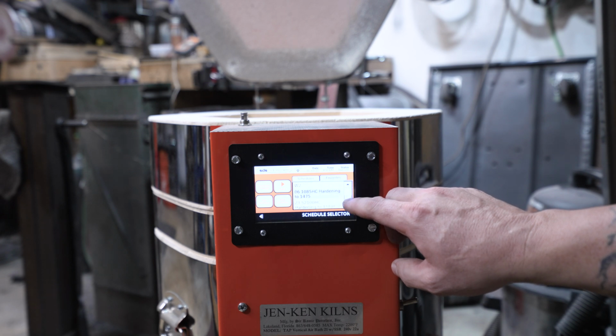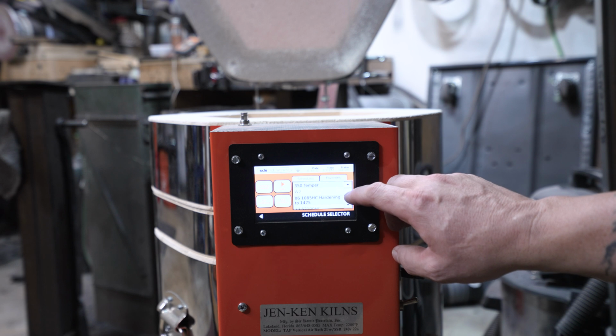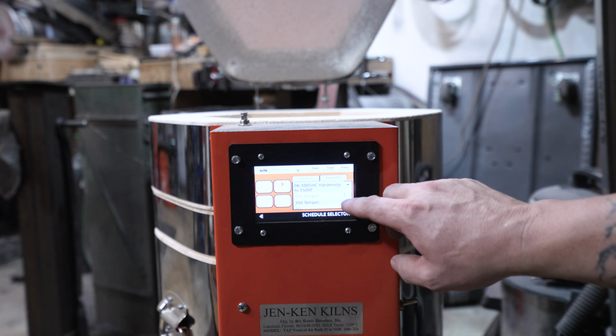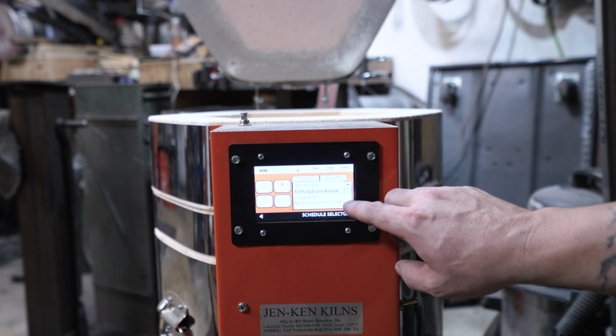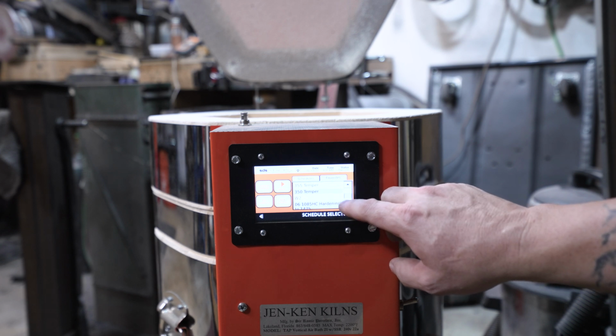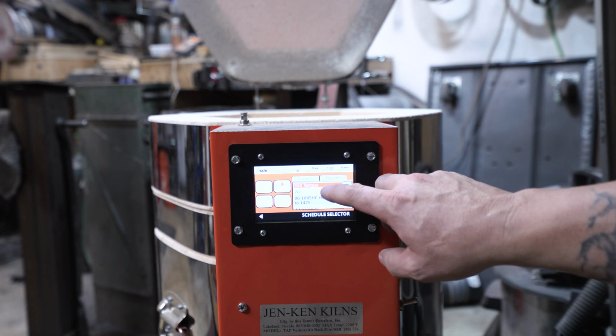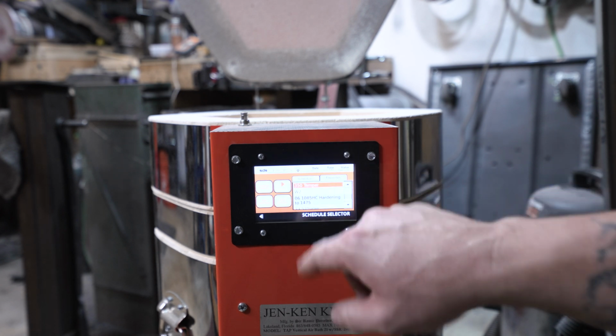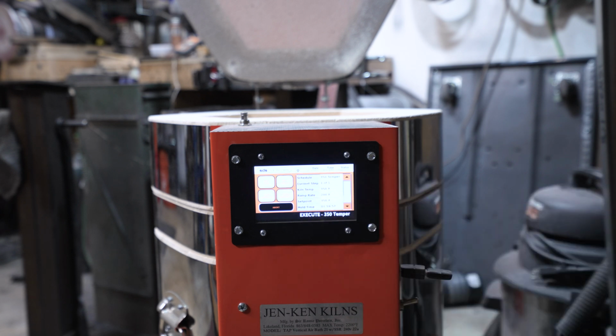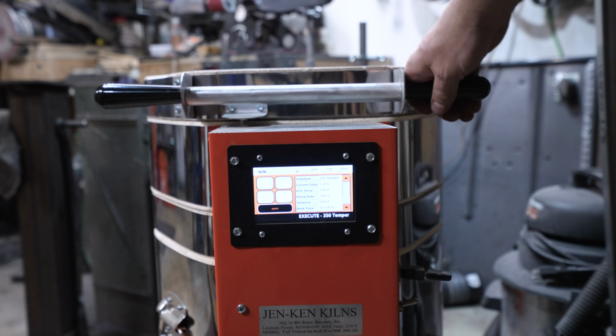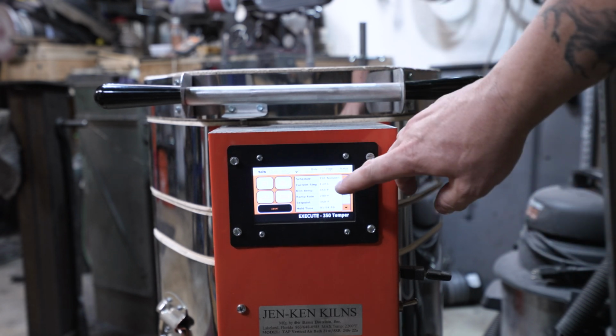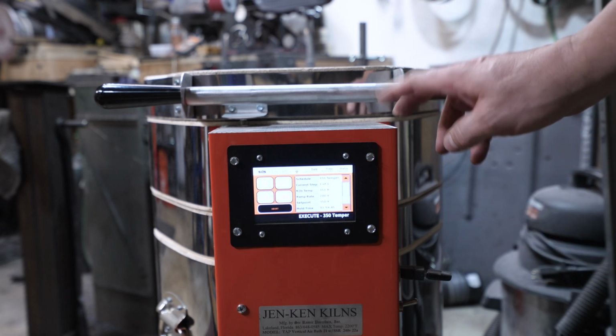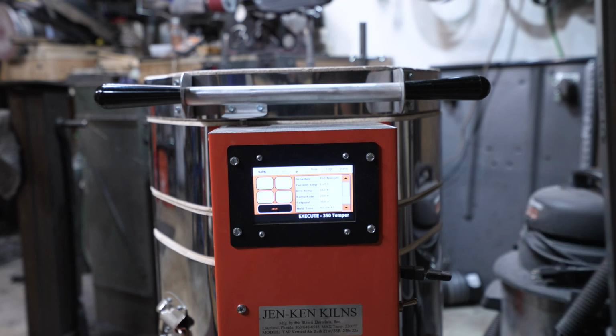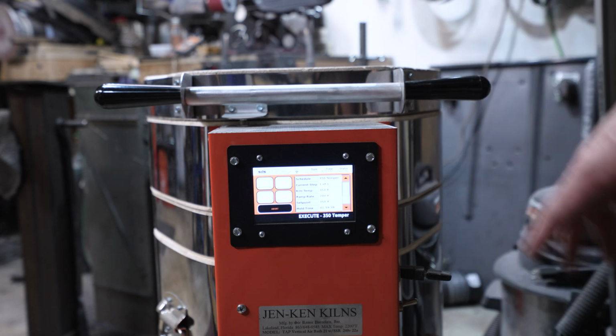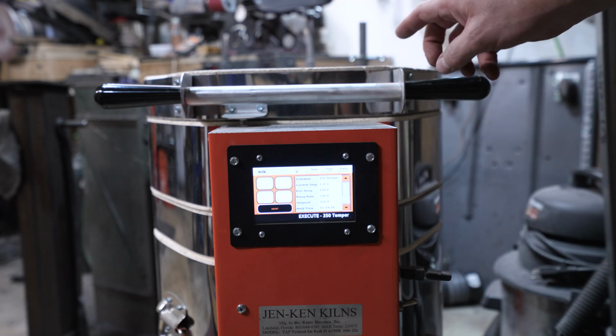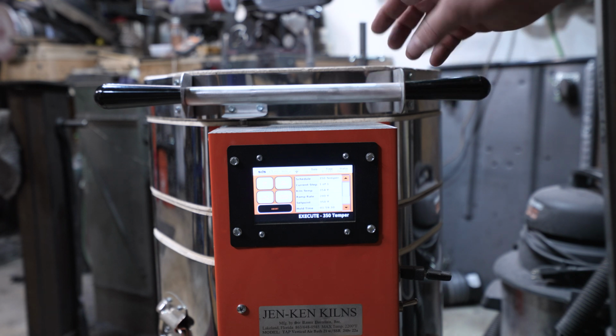So I have a few different temper schedules on here, and I have this one, where is it, 350 right here. So I have a 350 temper cycle, and what I like to do for the first little bit on this is kind of sit here and watch the temperature, because this is a schedule that I did, so my ramp speed and all that stuff should probably be adjusted to the point that it works a little better. But once the steel and the internal temperature of the kiln become equalized, then I can leave it alone.